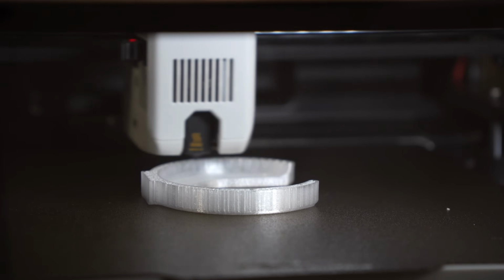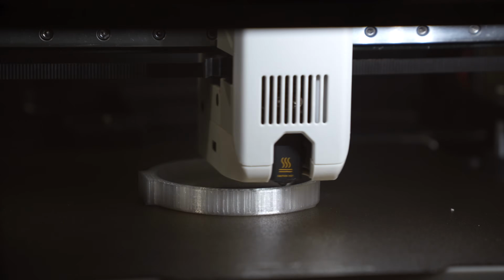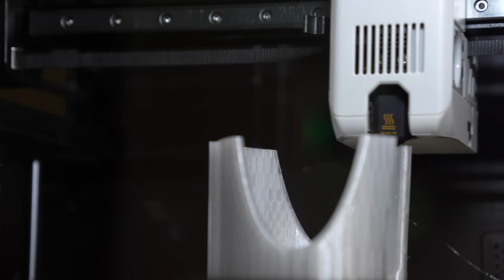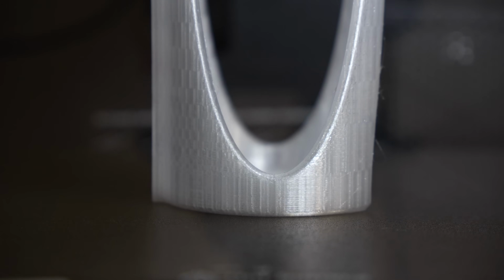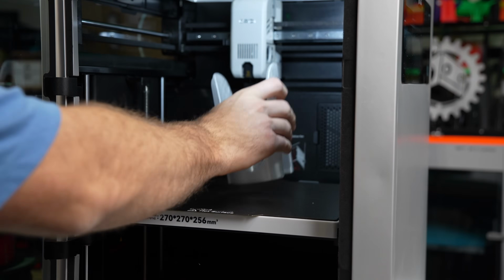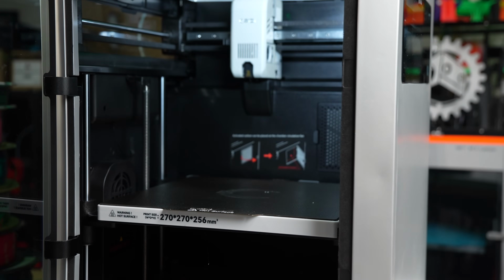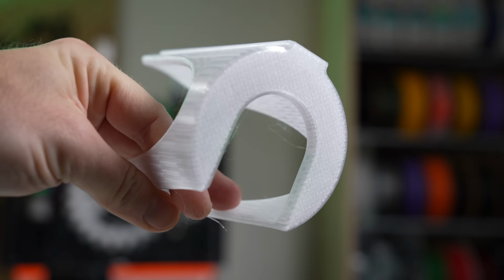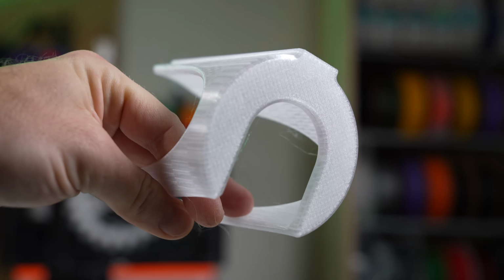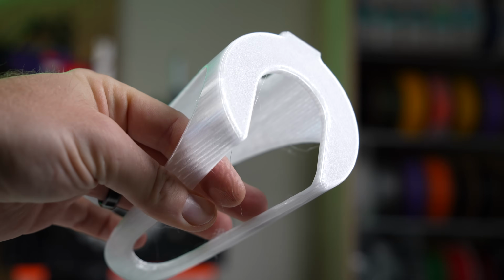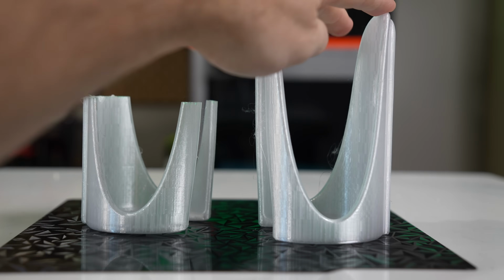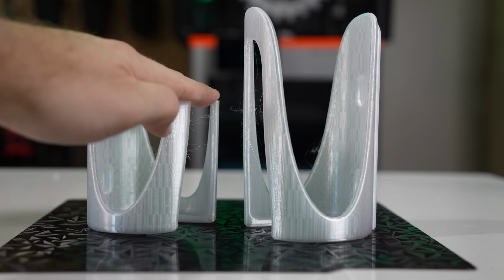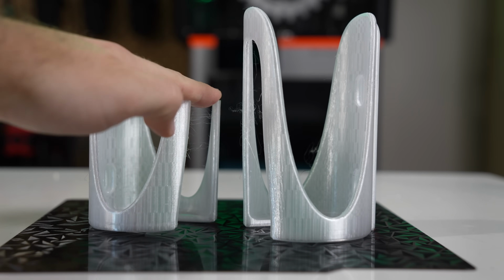Swapping to the side with the adhesive, I was up here sort of monitoring the print up to the halfway point, and I saw zero signs of warping. I still wasn't convinced that I wouldn't get at least a little bit of warping as it got further and further away from the build plate and got towards the top, but when the print completed and the plate dropped and I removed it, it was stuck firmly to the powder-coated PEI. This has largely been my experience with this adhesive when used for printing out ABS or ASA.